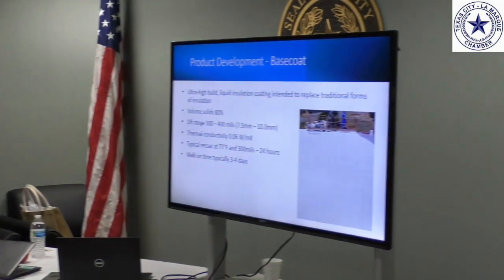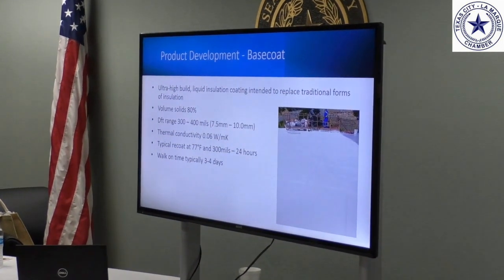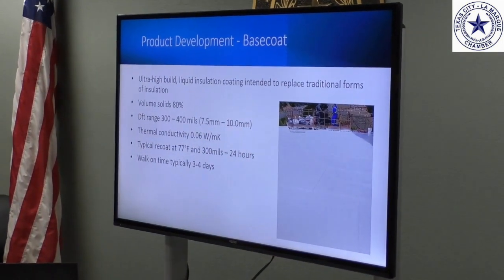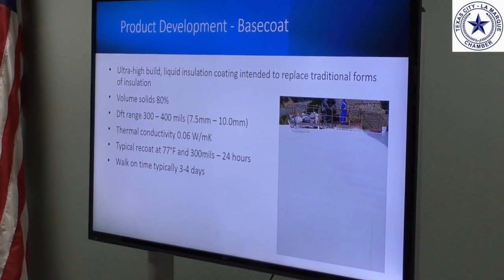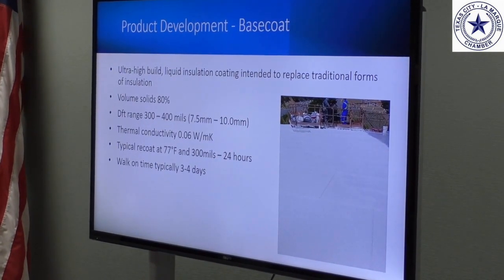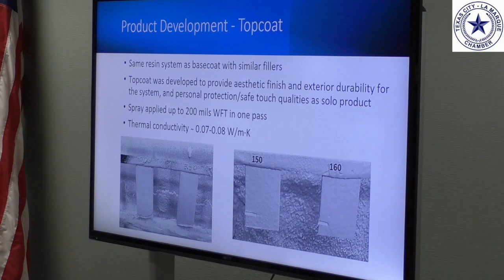Again, this is an application that we did at one of our industry partners, showing the base coat applied at 300 mils, 24 hours between coats, 3-day walk-on time, which is typical, 3 to 4-day walk-on time. The material is 80% solid, so you're not getting a lot of shrinkage. Shrinkage is reasonable, but not too much, so you don't have a lot of stress in the coating that causes it to crack and flake and so on.